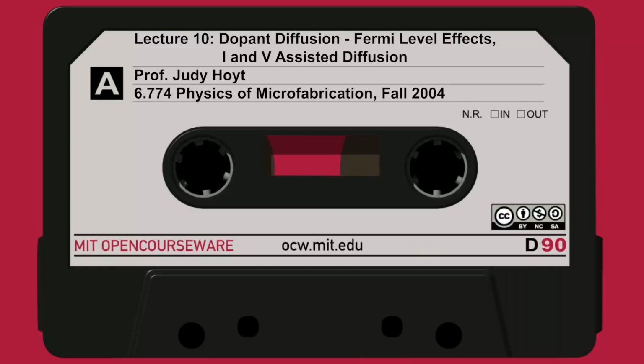So on page 33, I'm not going to derive this, but this is the actual overall flux equation that SUPREM uses, and it's discussed in your text. It's fairly complicated: the total flux of boron interstitial pairs is the product of all these terms. We can look at the terms and make sense of them. This dBi star, the star indicates it's inert, low concentration diffusion, driven by the dopant gradient, the usual good old Fick's diffusion.